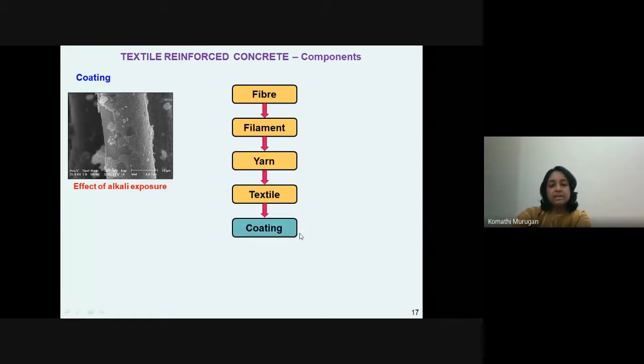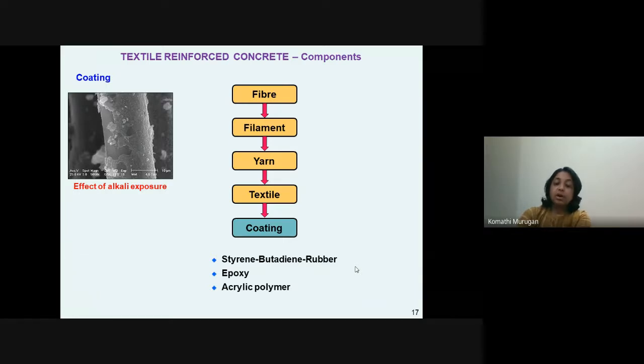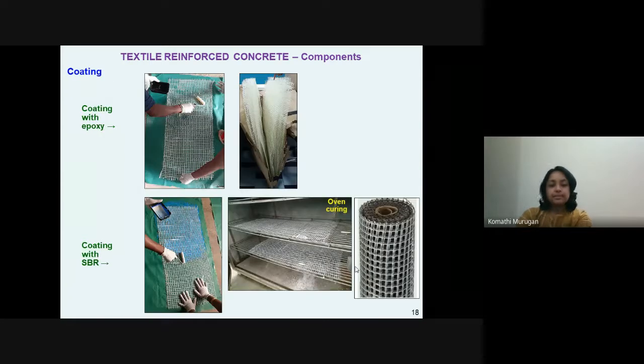So what we do essentially is something called coating. These textiles are to be coated with certain materials or chemicals which prevent the glass in the textiles from being affected by the alkali present in the cementitious environment around. Generally we use certain chemicals such as styrene butadiene rubber, epoxy, or acrylic polymers. These are the generally used chemicals to coat the textiles.